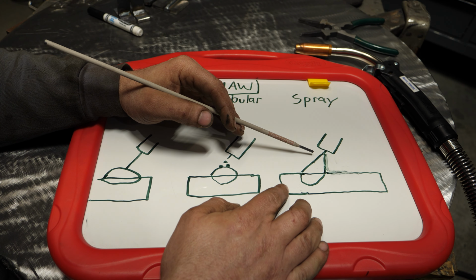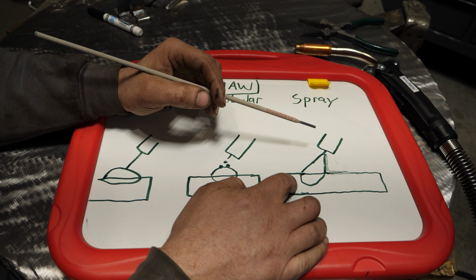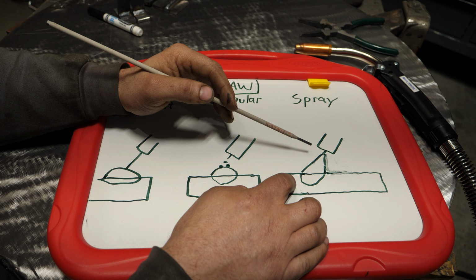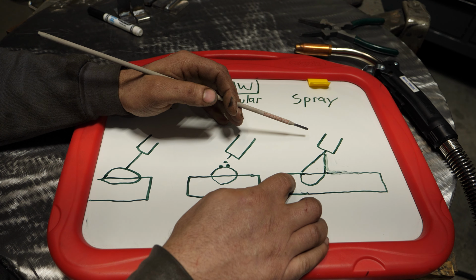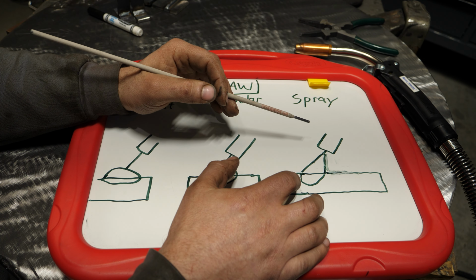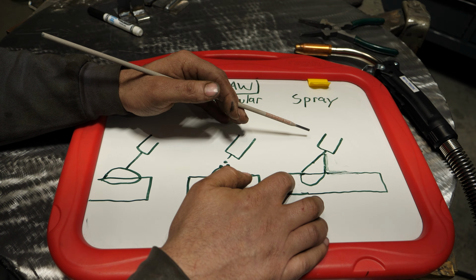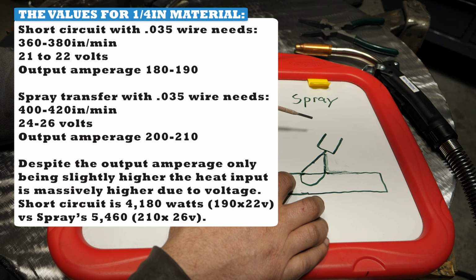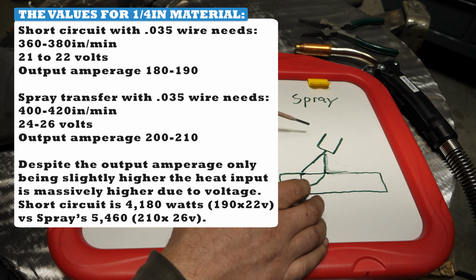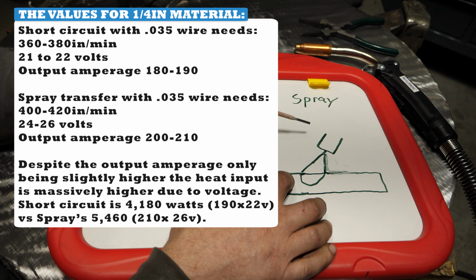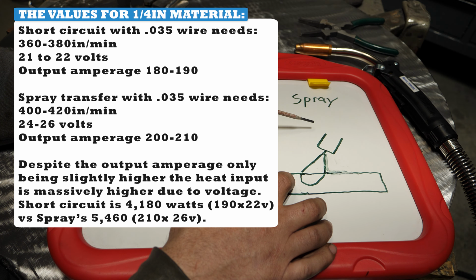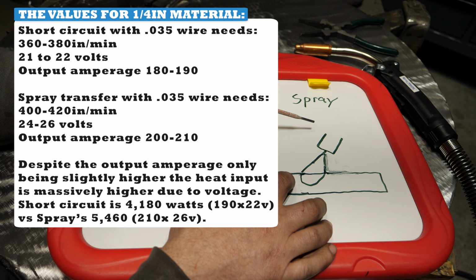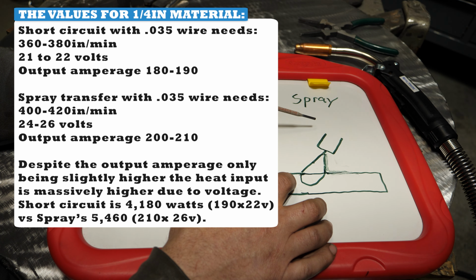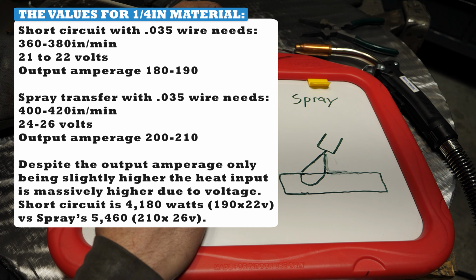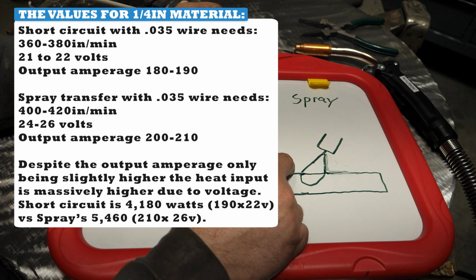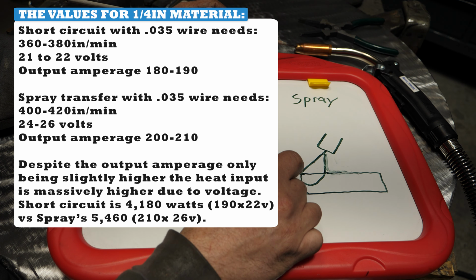The other limitation with it is most machines cannot do spray. It's not just an amperage issue, it's a voltage issue. And to give you a perspective on it, spray arc can be achieved with .035 wire at under 200 amps, but you need to be at 25 or 26 volts. Most home hobby machines are incapable of producing that kind of voltage at that kind of amperage output, which unfortunately will limit you to more or less the short circuit process and not spray simply because you cannot achieve voltage high enough to get to this.